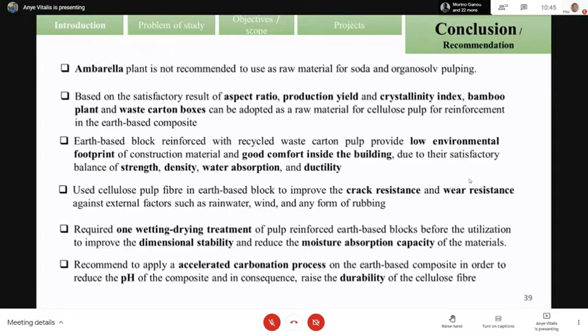That Ambarella plant is not recommended to be used as a raw material for pulping due to the fact that it has a high amount of lignin, so it can be used as feed for animals. Also, due to the high value of the aspect ratio, production yield and crystallinity index, we recommend bamboo and recycled fiber as a raw material to produce cellulose fiber as a reinforcement in the earth-based material for block application.